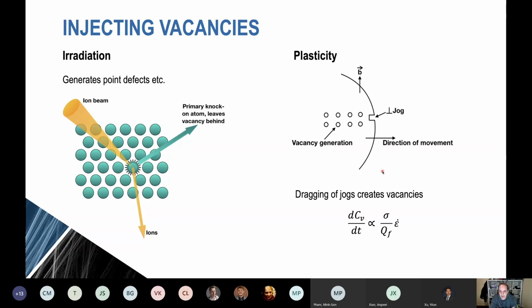And so we have some models to try and describe this vacancy generation approach. And one of them is shown down here. And it's a very, very simple idea. Really what we're talking about is we're using a fraction of the work done to create vacancies. So dC/dt is simply equal to the stress times the strain rate divided by the vacancy formation energy. And it's a very simple idea that you're using a fraction of the mechanical work to create vacancies.